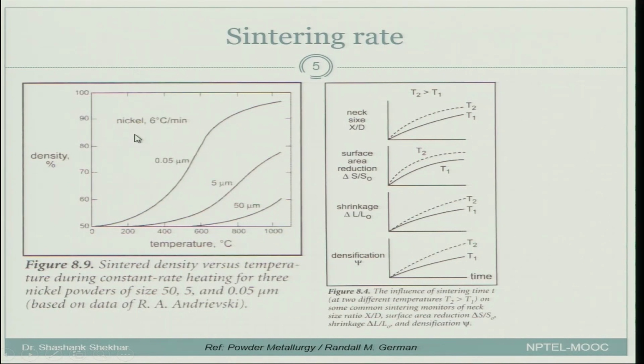In this particular case, nickel particulates were heated at a rate of 6 degrees Celsius per minute, and 3 different sizes of nickel were taken: 0.05 micron, that is 50 nanometer, 5 micrometer and 50 micrometer. At very low temperature, the 50 nanometer nickel particulates start to densify, and it reaches very close to 100%, in fact, by the time it reaches 800. On the other hand, as you keep increasing the particle size, the growth takes place at a later temperature. In the 5 micrometer case, it starts somewhere at 400 or 350, and by the time it reaches 800 degrees Celsius, it is only 65% densified. For 50 micrometer, it has not even started by 600, and at 800 it is just close to 55% densification.